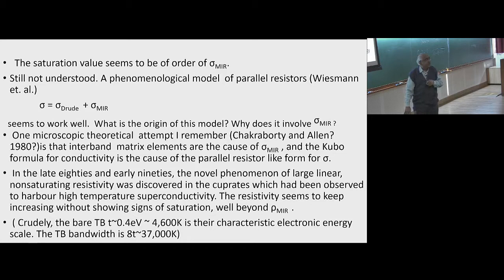But the thing which I wanted to show was the following, that in bismuth doped high-TC superconductor, which is abbreviated as 2201, whose superconducting transition temperature could be 8 degrees, could be 6 degrees, could be 0 degrees, Martin, Fiory, and others at Bell Labs found that the resistivity, electrical resistivity from 7 degrees to 700 degrees was linear in temperature. So 7 degrees is particularly low because its Debye temperature is of the order of 300 or 400 degrees Kelvin.